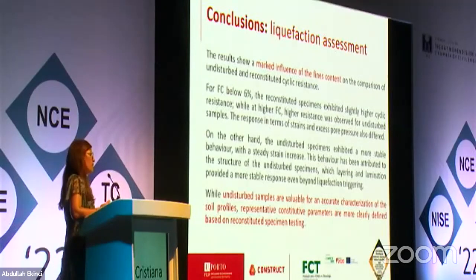So for very low fines content, we have reconstituted specimens with slightly higher resistance, but predominantly the response of the undisturbed samples was higher and more stable. And this behavior obviously is attributed to the layering. I mean, the clay layers are reducing the possibility of the excess pressure buildup, and that contributes very significantly to a more stable response, a smoother evolution towards liquefaction.